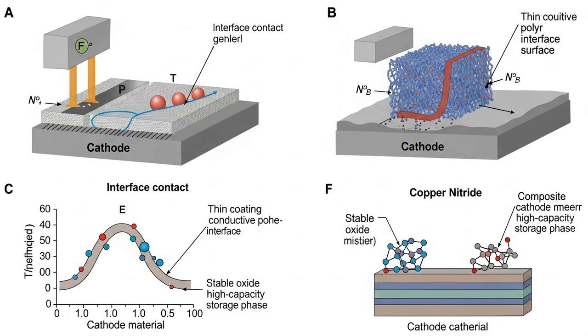To fix this, scientists are developing special coatings for the cathode particles that act as a buffer, or creating composite cathodes where the electrolyte and cathode materials are mixed together like a perfectly blended cake, ensuring there's a path for ions to travel everywhere. The unique environment of a solid-state battery is also allowing for totally new cathode chemistries. For example, recent breakthroughs with a material called copper nitride have shown it could have more than double the capacity of today's cathodes, potentially enabling that 1,200-kilometer range we talked about.